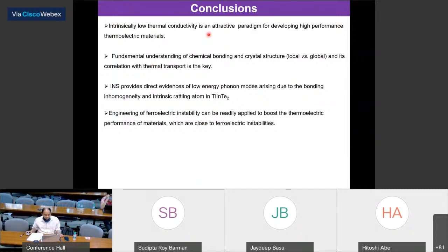Intrinsically low thermal conductivity is an attractive paradigm for developing high performance thermoelectric material. Fundamental understanding of chemical bonding and the crystal structure, especially local versus global structure, which can be probed by X-ray PDF very easily, and its correlation with thermal transport is the key to make good thermoelectric material. And of course, experimentally obtaining the phonon density of states or phonon dispersion is possible by inelastic neutron scattering experiment, which can be done at RAL, UK. So we have used both the facilities well, and we have shown for the first time that this ferroelectric instability can be readily applied to boost the thermoelectric performance,